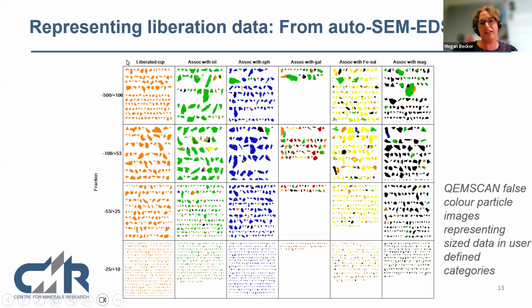And this category here, I've written an algorithm that tells me which particles to put in this block. And then I've said, if it's not liberated, I want to know the particles that associate with silicates, with sphalerite, with galena, with iron sulfides, so this is pyrite and pyrrhotite, and with magnetite. So now I can look at the characteristics of the particles, and I can understand what's happening in the system.